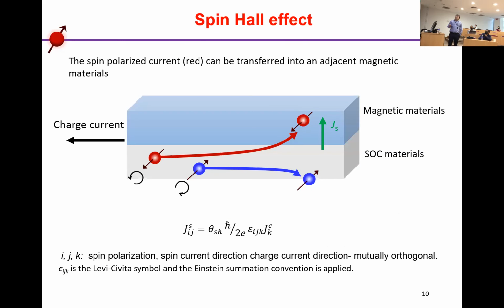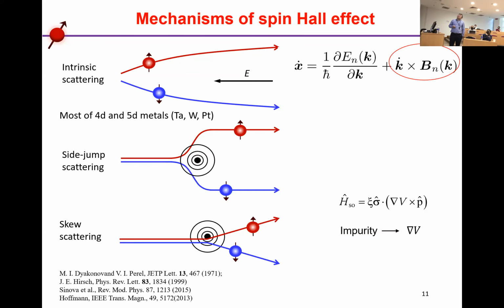This spin Hall effect is actually due to the charge current passing through the heavy metals, which generates a spin current. For example, here the spin current is along the vertical direction, and the polarization is in the y direction. Then this spin current, with the polarization in the y direction, exerts torque on the ferromagnetic layers.